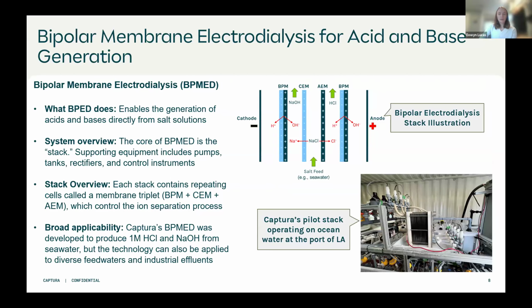So, getting a bit more into membranes and electrodialysis, I already reviewed this stack idea, but as I mentioned before, we have a bipolar membrane, a cation exchange membrane, and an anion exchange membrane that allow us to make acid and base from our saltwater feed. When you take this unit, we call that a triplet, and then you can repeat that triplet as many times as makes sense in between your two end electrodes.